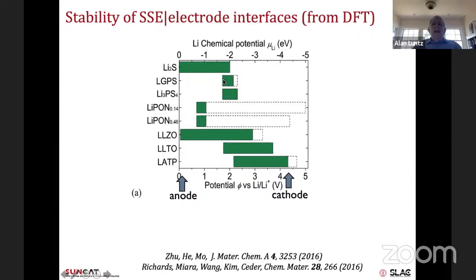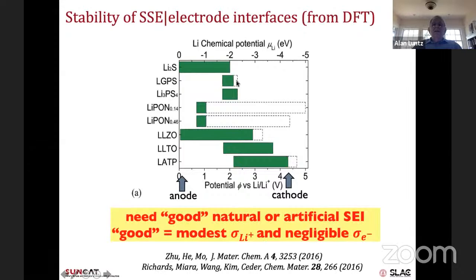They're unstable at both the anode and cathode. A few are stable at the cathode, but not many. These are not high conductivity materials. So you need either a good natural SEI to isolate them or an artificial SEI, which means a coating, usually on the electrode particles. Good means it has to have pretty good lithium-ion conductivity but poor electrical conductivity, so that the growth of the SEI terminates because you can no longer have redox reactions with the electrolyte through it.